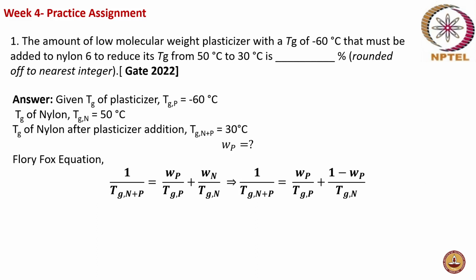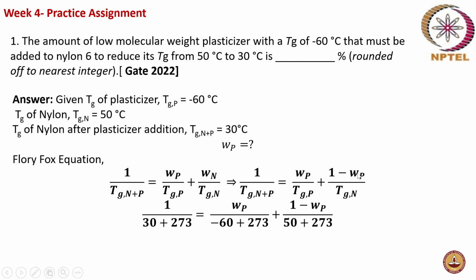That is what I have done here, right? You are able to figure that out, right? Because it's only two components. So if you know the weight fraction of one, the weight fraction of the other will be 1 minus the weight fraction of the first one, right? So that is what I have done for the weight fraction of nylon. And then you just have to substitute. Here again you have to take Tg. Tg they have given in degrees Celsius. You have to convert it into Kelvin.